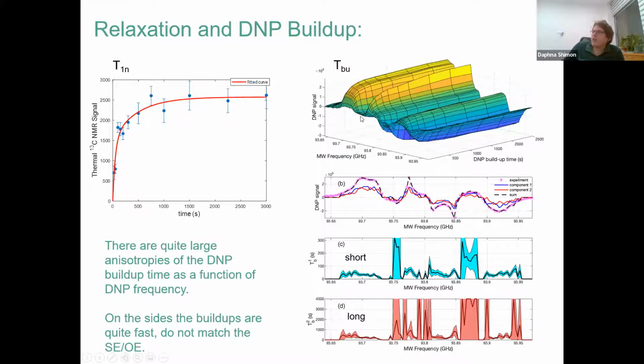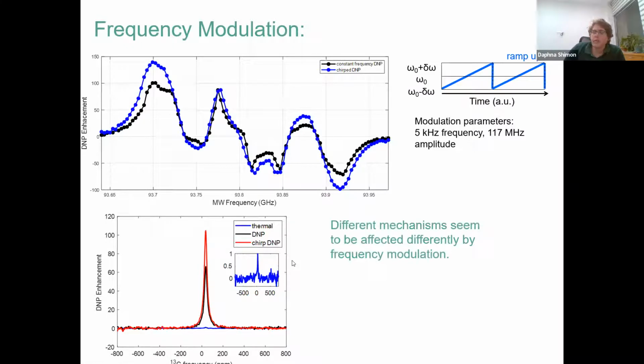Also notice that there are some small features in the DNP spectrum where the buildup time is very long. So we see only low enhancements at those frequencies, but if we waited longer, we would probably get larger features. That's interesting to think about for some future work. The main point here is that the timescales on the sides are slightly shorter than the timescales in the center. And that suggests that what we're seeing on the sides of the DNP spectrum is maybe not an Overhauser effect, and maybe something else. The last thing that we can do is look at frequency modulation.